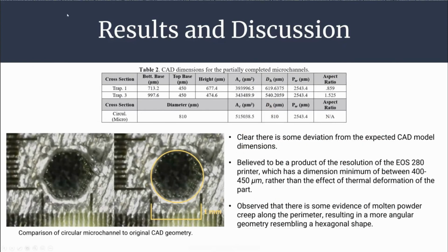So although there were no successful prints of the heat exchangers thus far, we can analyze some of the prints that were partially printed. And we had two trapezoidal and the circular cross-sectional area as well. And you can see in the left-hand picture there that it maintains mostly its circular shape, but you can start to see the limitations in the resolution of the printer because you wind up with kind of an almost hexagonal perimeter there, as opposed to a purely circular one. But an analysis of this would lead to whether or not these deviations from the CAD model are really going to affect our friction factor or our hydrodynamic performance experiments.